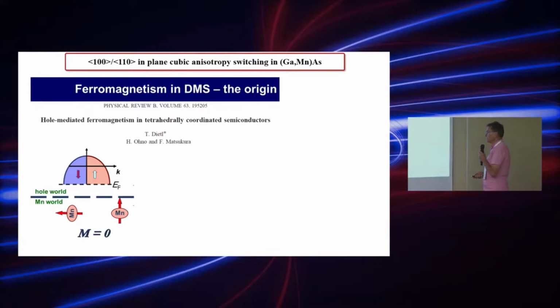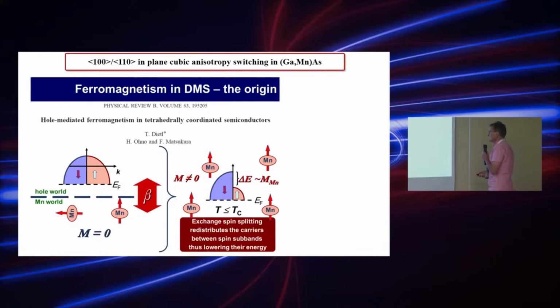If these 2 worlds are independent, if there is no coupling between them, then the manganese spins are basically uncoupled, or there is a weak antiferromagnetic superexchange between them, and these 2 worlds simply live on their own. However, when the coupling is introduced, it turns out that it pays for the system to polarize all these manganese atoms, so they create non-zero magnetization, and in the presence of this exchange field due to this magnetization, the valence band of holes splits. This redistribution of the carriers lowers the energy of the carriers, which provides additional energy gain. So then the entropy penalty imposed by the ordered manganese ions can be compensated.